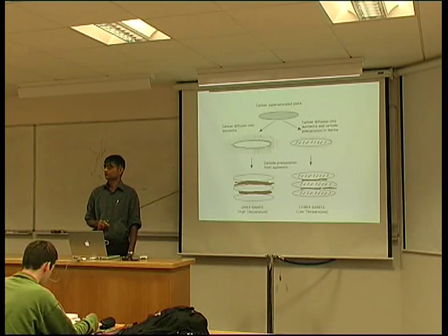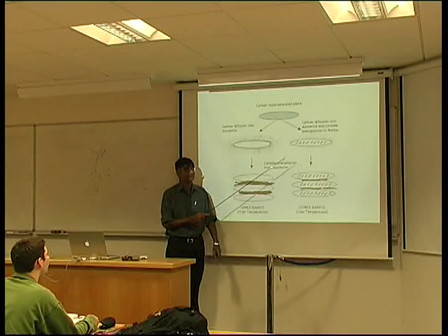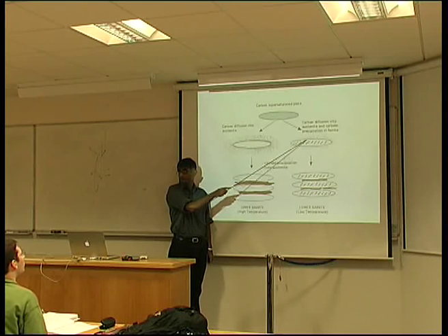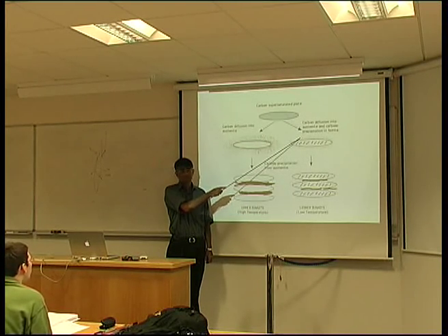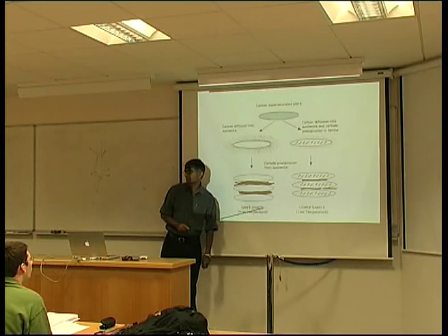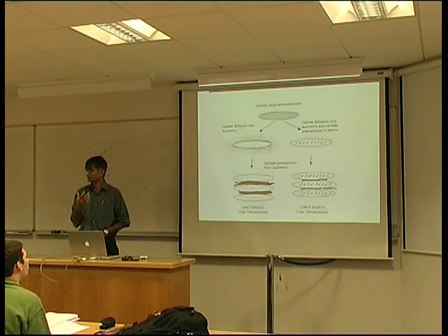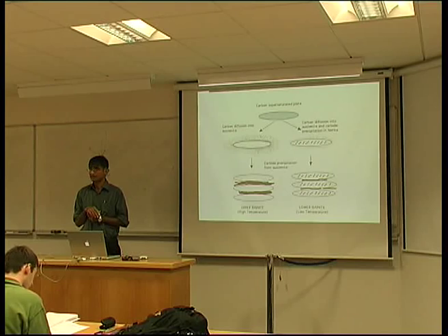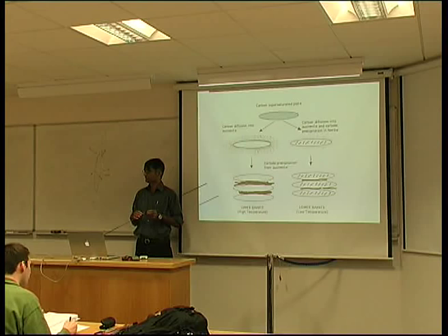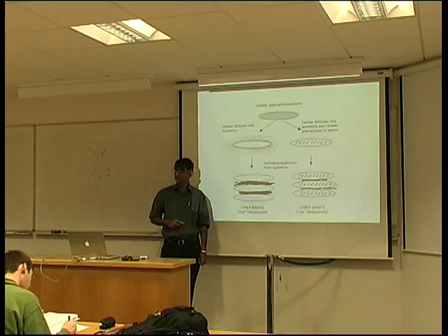Now, if we transform this at a lower temperature to generate lower bainite, then the time required for diffusion is greater, so you have an opportunity to precipitate inside the plates of ferrite. Some carbon escapes and then precipitates between the plates. And that generates the microstructure of lower bainite. Now, we need to prove that this actually is the mechanism and that the bainite actually forms completely supersaturated with carbon. If we can prove that, then the entire microstructure is explained.